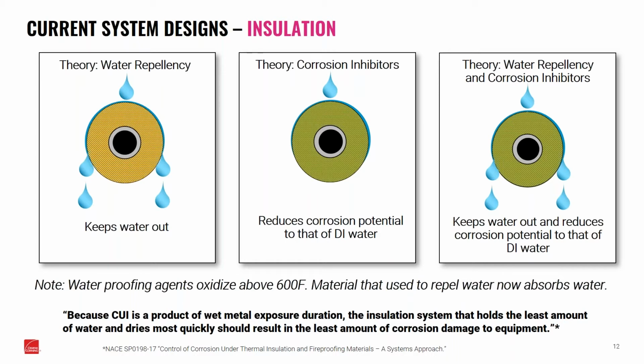Now, I think looking at all of these, and we see all three of these in the marketplace, I always come back to this statement at the very bottom made by NACE in their technical paper, the SP0198 paper that's out there, that because CUI is a product of wet metal exposure duration, the insulation that holds the least amount of water and dries most quickly should result in the least amount of corrosion damage to equipment. So to me, again, the best way to deal with these problems is to keep moisture out of the insulation to begin with.